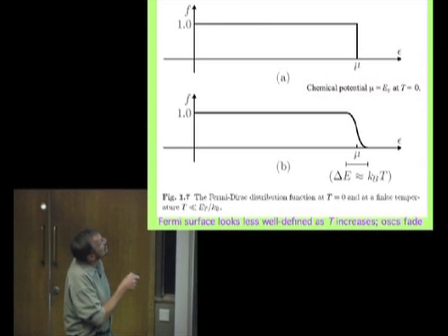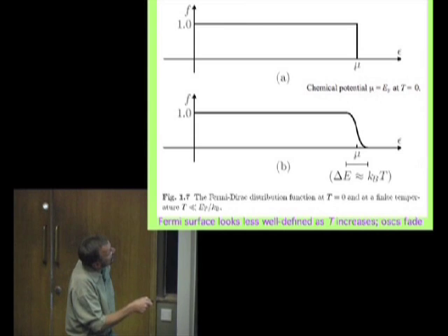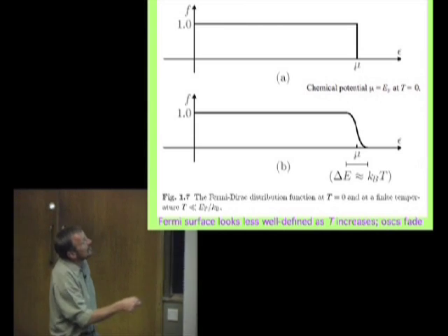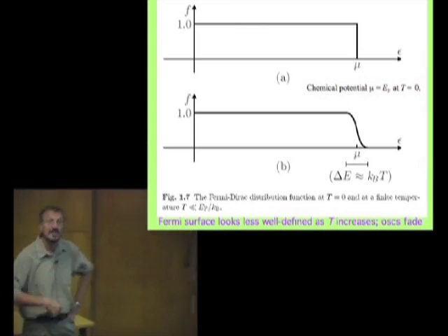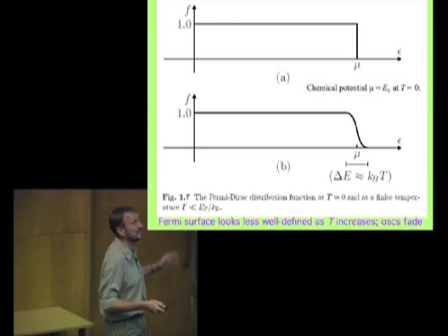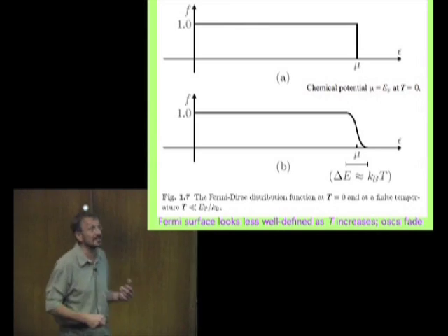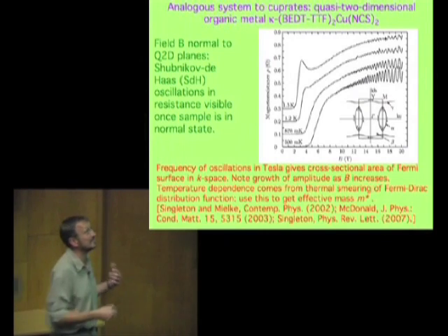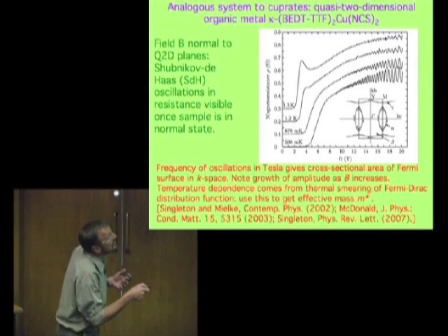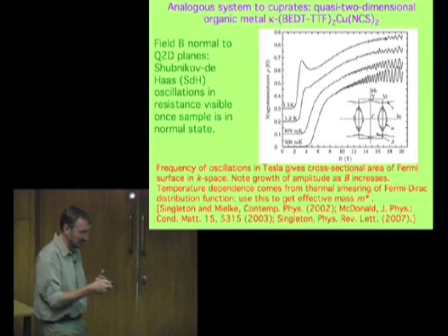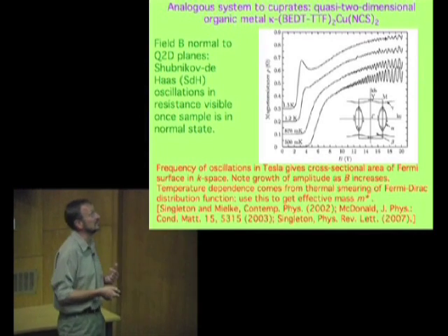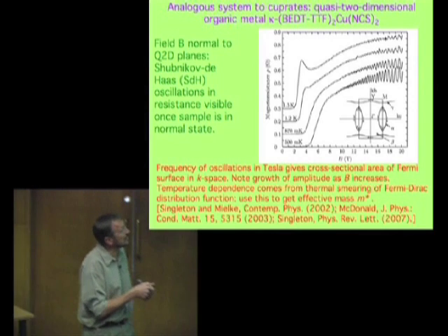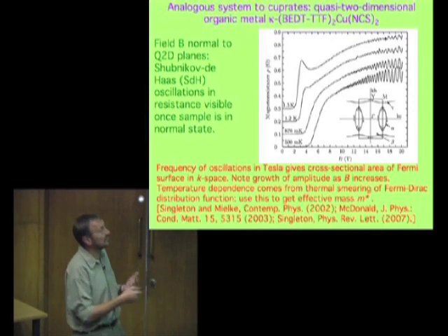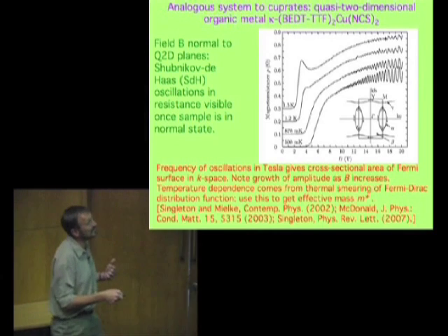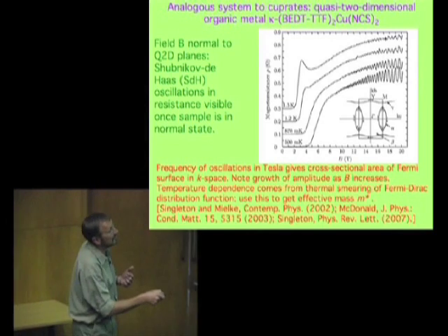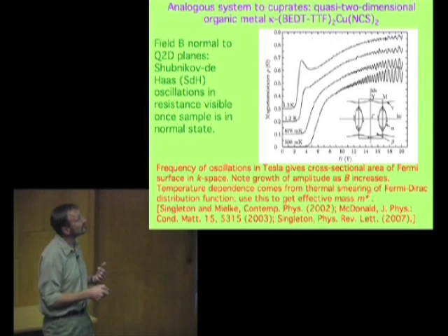At higher temperatures, the Fermi surface gets smeared out by a broadening which is about of order the temperature. So as you raise the temperature, the Fermi surface stops being a sharp-like thing, it's a fuzzy thing. So rather than going through a sharp entity in K space, the energy levels are now going through something fuzzy, which is why the oscillations drop off in amplitude. But this is a nice thing because we can compare the energy level spacing, which you remember depended on the effective mass, and the temperature, and we can get the effective mass out of this.